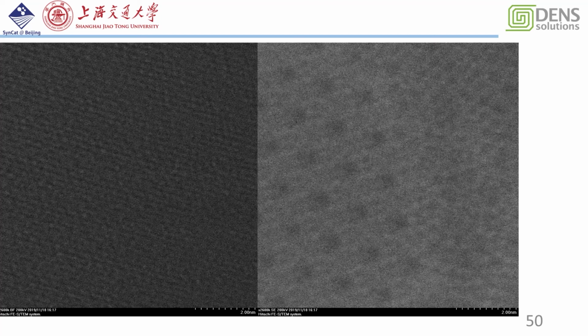And here is a very interesting image. This is even higher magnification, about 2 million times. This is a dark field image of the nanoparticle found in situ under the hydrogen atmosphere. And we can see the lattice from the dark field images. But here, this is the secondary electron image. They suggest the iron oxide surface has a very complicated feature during the reduction. And these features could be related to this reduction behavior.